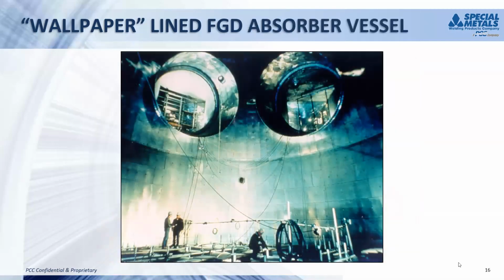The next slide shows a similar type of construction. This was an FGD absorber vessel. Originally, it was planned to rubber coat the vessel. It was fabricated from steel and it was going to be rubber coated. Unfortunately, when it came time to install the rubber, they couldn't find a group that was satisfactory for the job. So they redesigned and decided to use alloy C276 wallpaper. And it was installed very similar to the duct you saw earlier. About the same size sheets, and plug welds, again, were used to reinforce the attachment of the cladding to the wall.